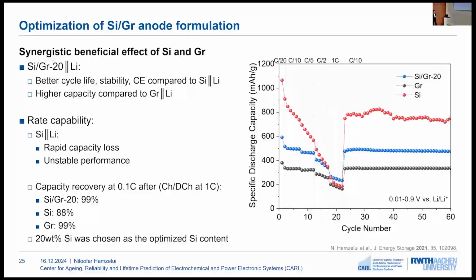The rate capability of these cells was also investigated at different C rates, and afterwards the cells were measured again at C/10 to measure the capacity recovery. It can be observed that for the pure silicon electrode, we have a more rapid capacity loss, an unstable performance, and also lower capacities at high C rate. After measuring the capacity recovery at C/10, it can be observed that for the composite electrode and for the pure graphite electrode, we have 99% capacity recovery, while this value is 88% for the pure silicon electrode.